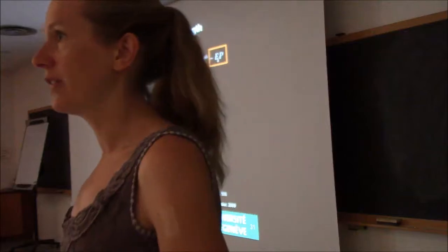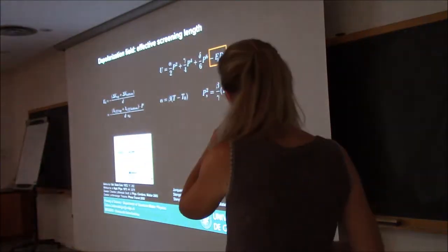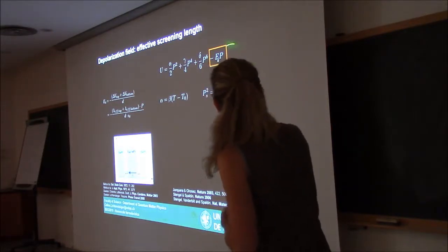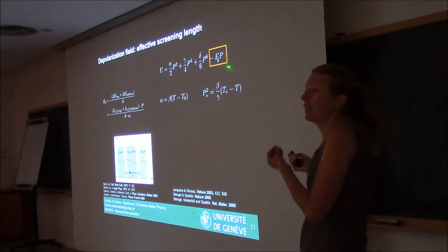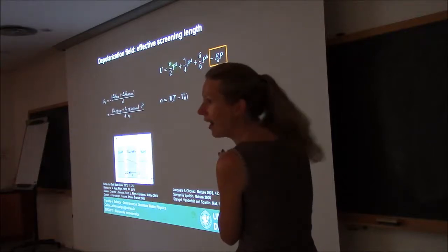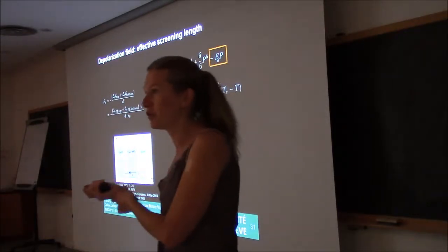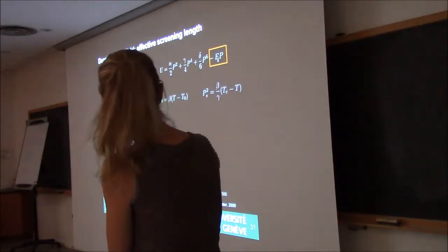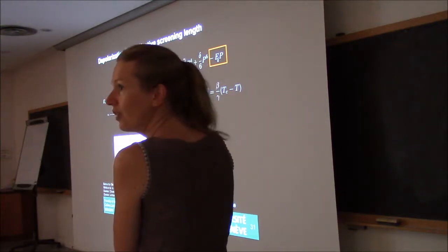So again, you see easily that to reduce this energy cost, you will have to either reduce the depolarization field or reduce the polarization. Because E goes as P, here that means that you are adding a positive energy term that goes as P squared. So P squared means that you can rewrite this by changing your alpha term. If you remember, what happened with the strain effect was changing this alpha and gamma term. So here you are changing the alpha term that gives you the transition temperature, and because you change the transition temperature, it will also change the polarization.